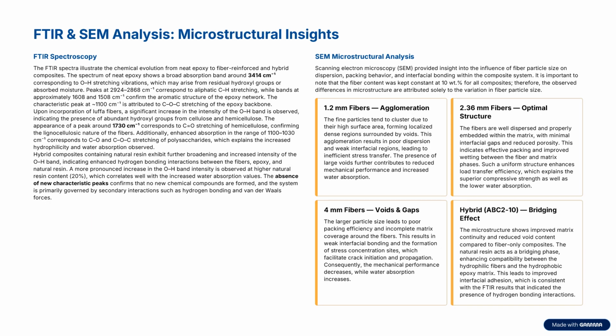The FTIR illustrates the chemical evolution for neat epoxy, fiber, and hybrid composite, and we have the spectrum of OH, CH, and C-O-C. The hybrid composite with natural resin exhibits further broadening and increased intensity of the OH band, indicating enhanced hydrogen bonding interaction between the fiber, epoxy, and natural resin.